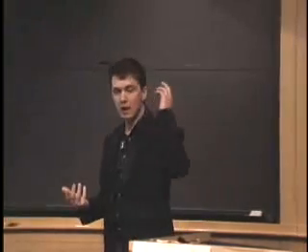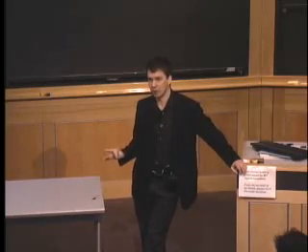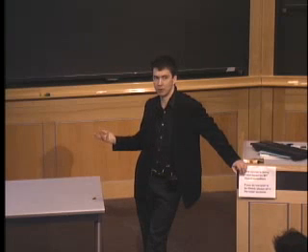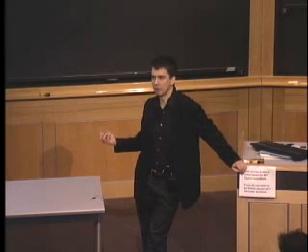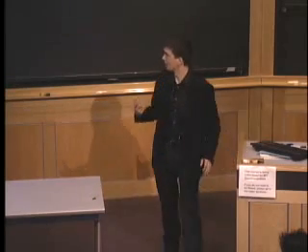See, a lot smaller because you're counting now bond strength in coordination 12, where every bond is weaker. So you try to map that onto a pair potential, and you get, in some sense, a much weaker interaction per pair. Okay. And what Anders Carlsson did, he also extracted it from phonons. This one is really small, and from defects. And the defect one even has a different minimum. Actually, they all have a different minimum.